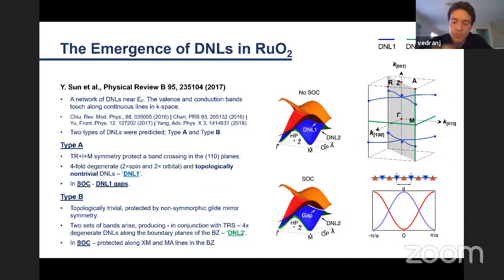In the presence of spin-orbit coupling, these Dirac nodal lines are supposed to gap, as I showed you in these two simulations, and this is expected to produce, for instance, large intrinsic spin Hall conductivities, etc. And then the intersections of all of these points are shown here as the hexatuple and octatuple points, and essentially it's quite a complex band structure predicted by these symmetry principles.